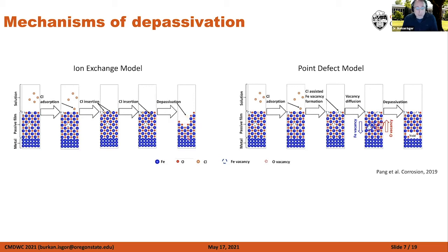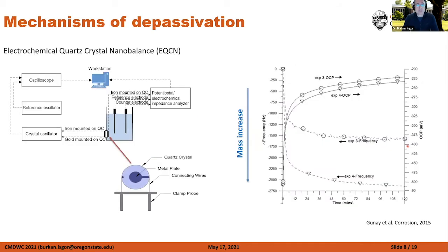Some people show a different way of passive film destruction, but at the end of the day, this whole model is based on the implication that chlorides need to diffuse into the passive film. There is another approach in which the chlorides are not necessarily diffusing into the passive film, but actually creating some iron defects, iron vacancies, and those vacancies diffuse and create basically a defect structure at the metal and passive film interface. Again, testing these are difficult.